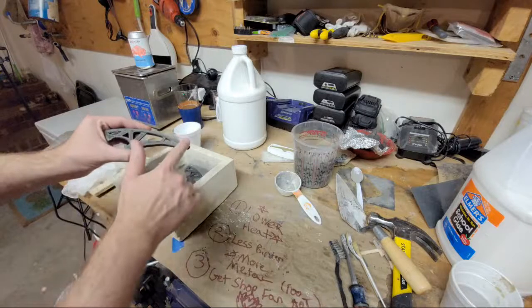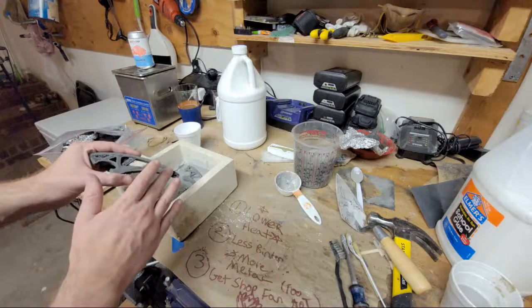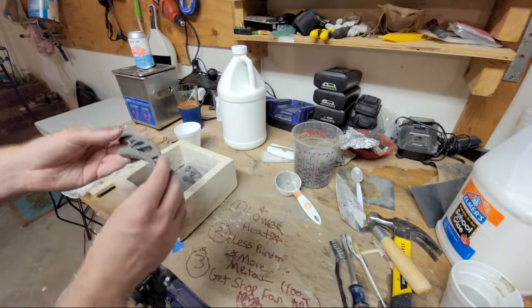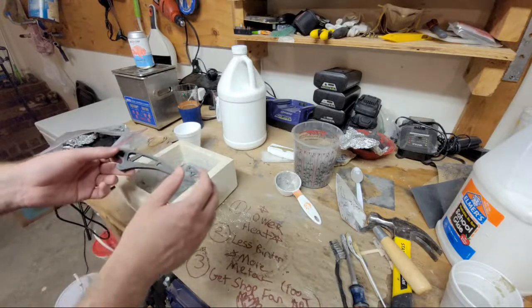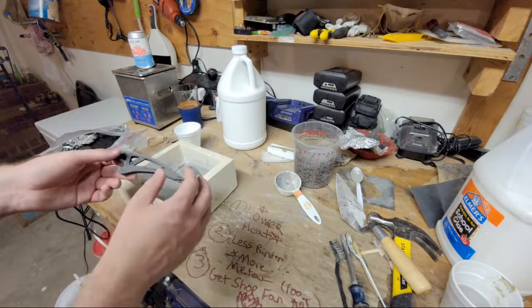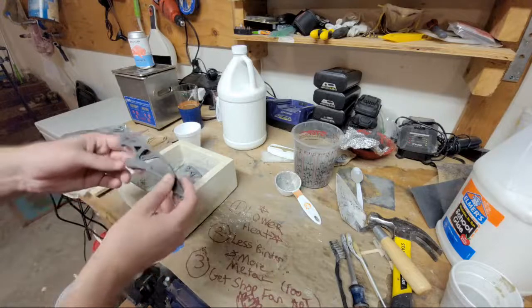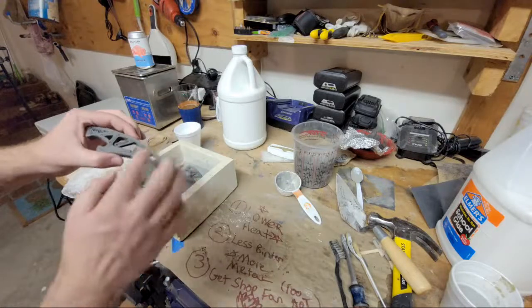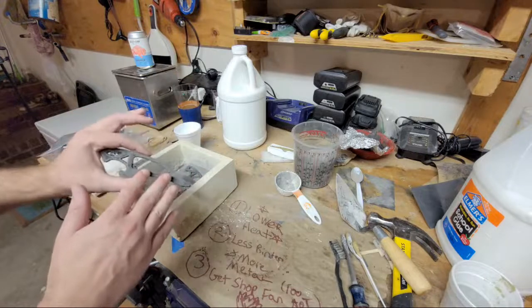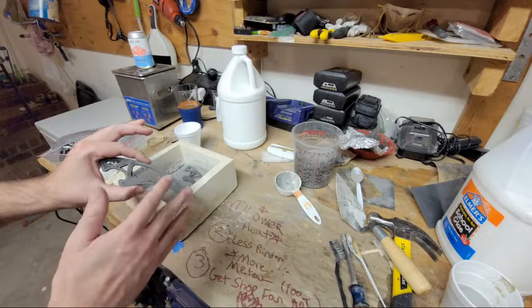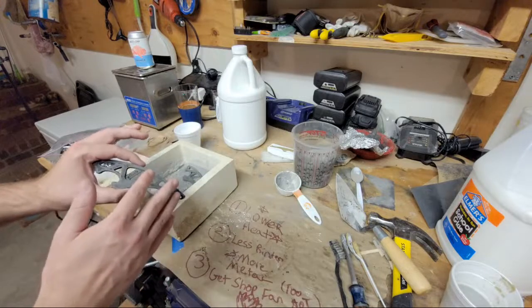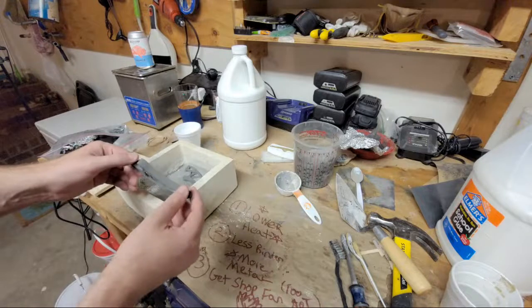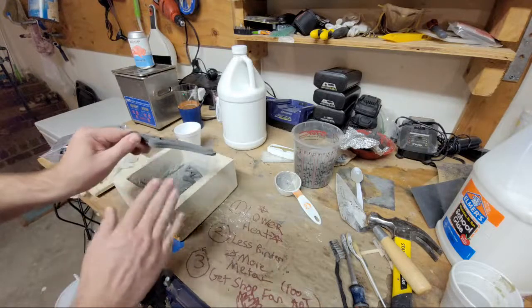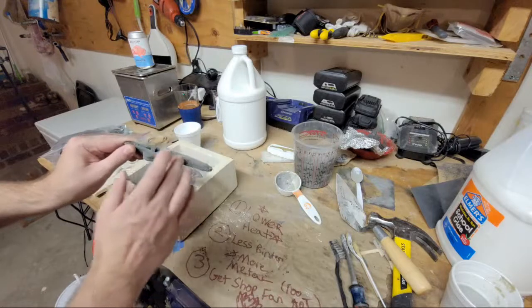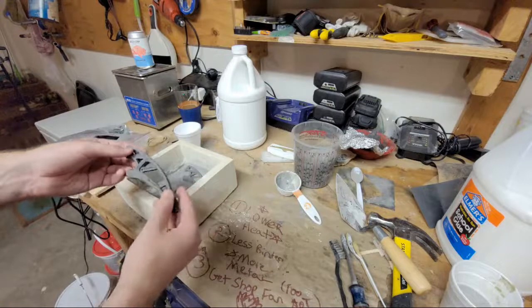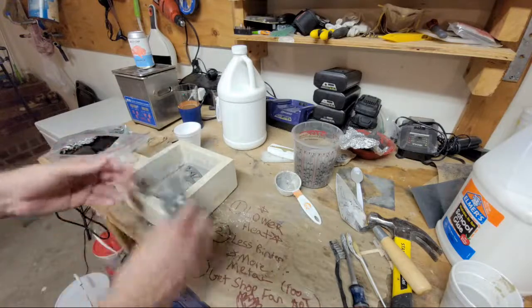The metal that I'm alloying with is copper, and the reason that I picked copper is due to its relative melting point to the sintering temperature of the steel. The steel that I'm going to be doing here is 17-4. We're going to be sintering it at a lower temperature, but still very high. It's about sintering it around 2040 degrees Fahrenheit, and the melting point of copper is below that. So the idea is that it will get sucked into this part, solidify it, and make it very strong, sort of like an alloy. Anyway, let's go ahead and get that prepped.